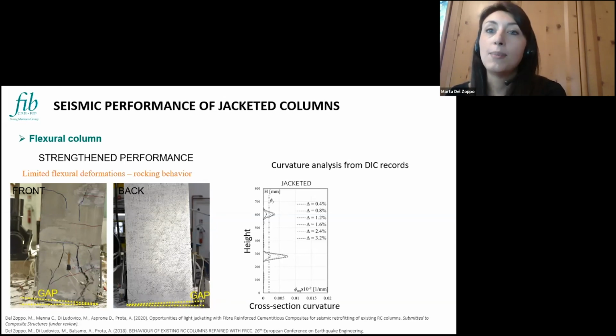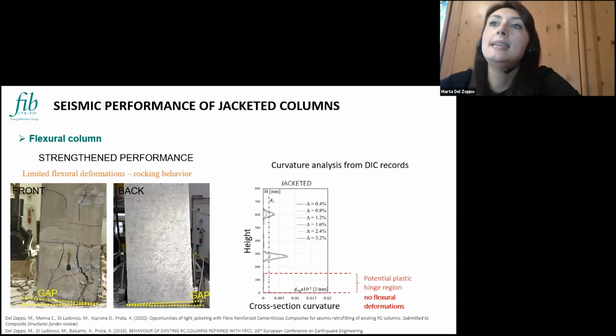So this is the plot of the cross-section curvature over the height of the specimen during the test for these different imposed drift ratios. And it is clearly visible that the curvatures in the potential plastic hinge regions are almost zero. That means that the flexural deformations are almost negligible for such a column, and that all the deformations are actually concentrated at the base interface in the form of base rotations.